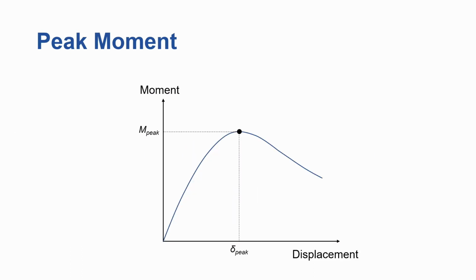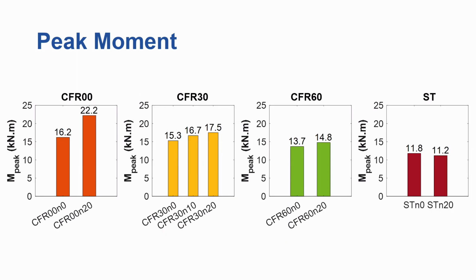The same thing with the peak moment. So at least for the axial load levels considered in the study, we saw that the peak moment increased as the axial load level increased, and then as the rubber content in the concrete infill increased, the peak moment reduced. However, this reduction is far less than what we see from the unconfined specimens, just when I showed you earlier the compressive stress strain responses. And this is mainly due to the steel contribution, and also the members here are subjected to bending as well, not just compression, as in the case of the unconfined compressive strength results.